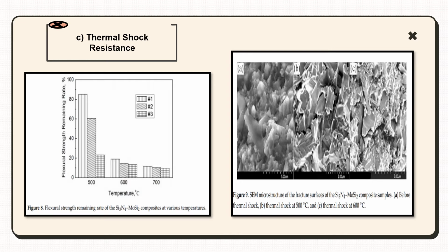Figure 8 presents the flexural strength remaining rate of the silicon nitride molybdenum disulfide composites at temperatures of 500 degrees Celsius, 600 degrees Celsius, and 700 degrees Celsius after thermal shock testing 10 times. As demonstrated in this figure, the flexural strength remaining rates were 85.2%, 60.5%, and 23.4%, corresponding to samples 1, 2, and 3 respectively, when the thermal shock temperature was 500 degrees Celsius.